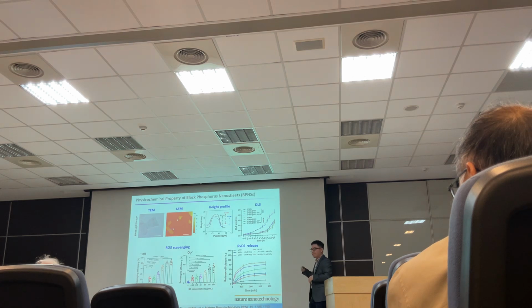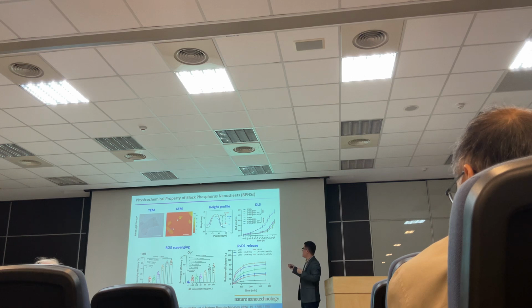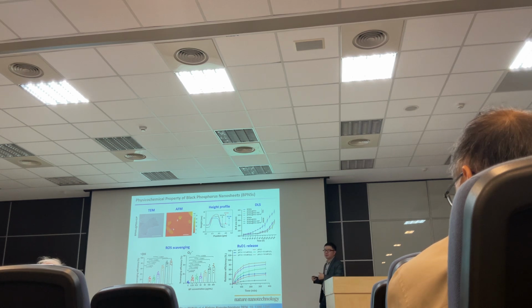And this is the basic characterization of our materials. As you can see here, the particle size is about 100 to 200 nanometers, and the thickness of the black phosphorus nanosheet is about 15 nanometers. Of course, because we modify the particle surface with PEG, the particle has very good colloidal stability in PBS and in the cell culture medium.